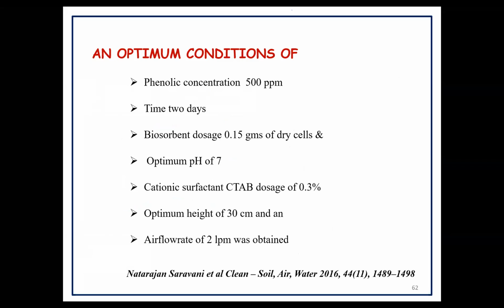So phenolic concentrations up to 500 ppm can be utilized. The time required for carrying out the experiments is 2 days. And the optimum pH is 7. So these are the CTAB dosage. CTAB is nothing but the surfactant, cetyltrimethylammonium bromide.